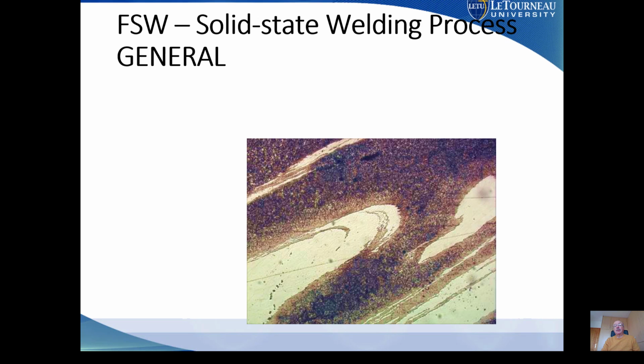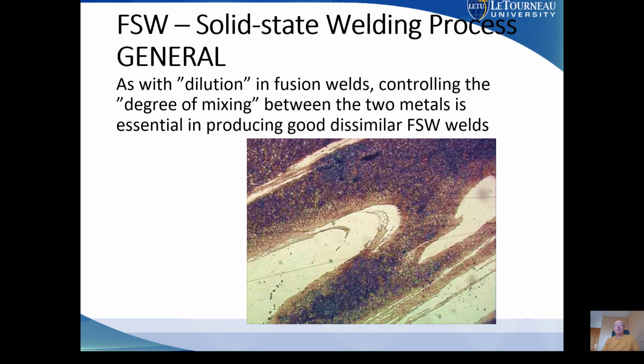the two materials, and you can see here white is aluminum and steel is the dark. This is kind of a solid state, kind of a flow together, locking the two materials together is really what happens. And so in fusion welds, we talked about dilution. When we have two materials, we kind of calculate the approximate average composition between the materials. In friction stir welding, we talk about degree of mixing. So how much we mix these two materials is really going to affect how well dissimilar friction stir welds are